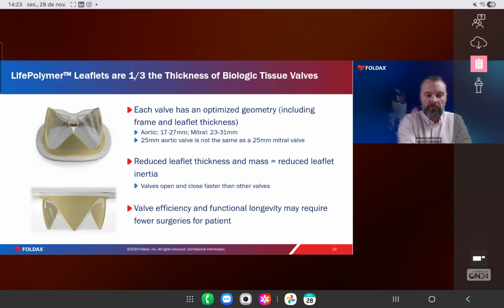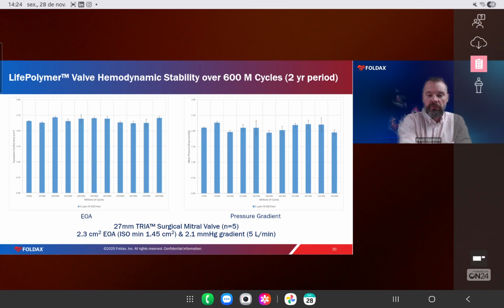And so it makes the valve much more efficient and gives it much more longevity, that again can last longer and hopefully require fewer surgeries for each patient. So that being said, we test this in vitro per ISO 5840, and we look at the effective orifice area and pressure gradient over time. We do this under an accelerated wear condition, and this is for one of our mitral valve sizes, the 27 millimeter, with a number of them on test.